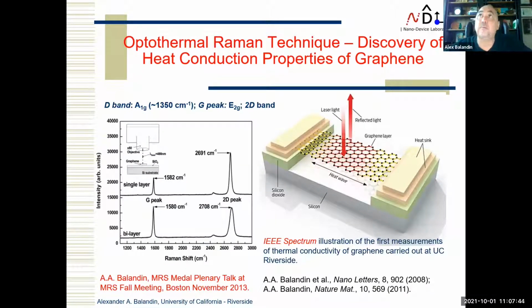Now I'll go faster with a few slides to tell what we have done and what we are doing. We developed this Raman optothermal technique in order to measure thermal conductivity of graphene. This is an illustration of the method. We suspended graphene over a trench in a silicon wafer, and we use the laser of a Raman spectrometer as a heat source. By increasing the power of the laser, we were able to heat up locally the graphene suspended over the trench, and we could measure local temperature by observing the shift in the G peak position. With some calculations, you can then figure out the thermal conductivity of this material.